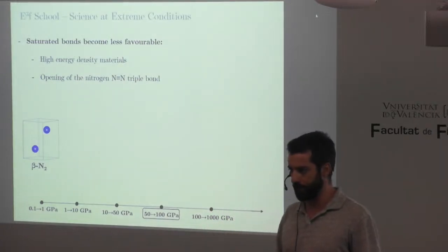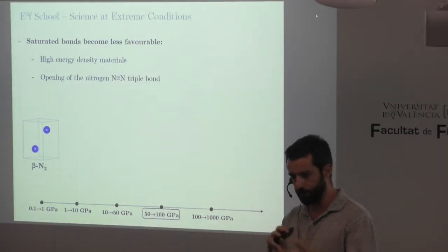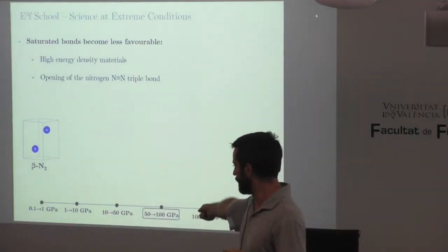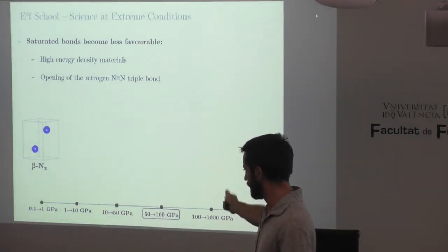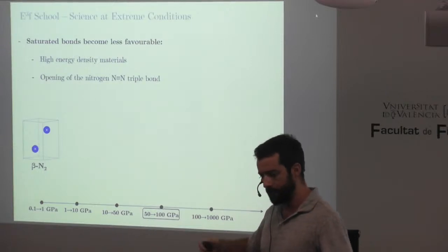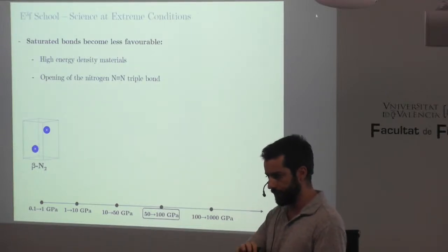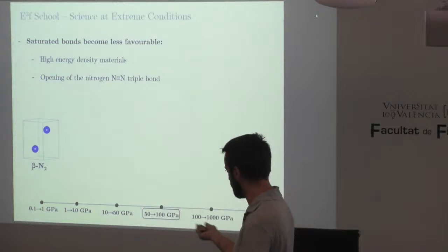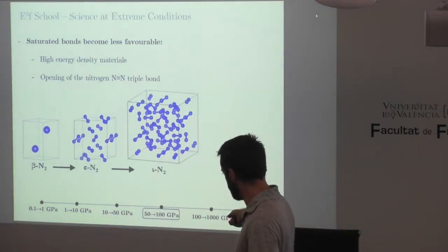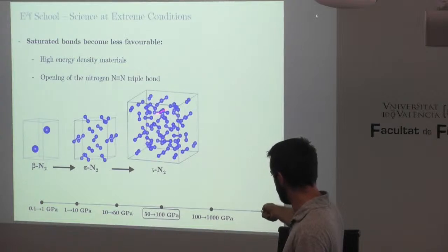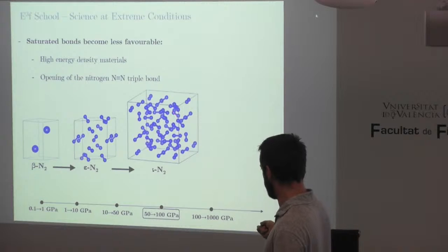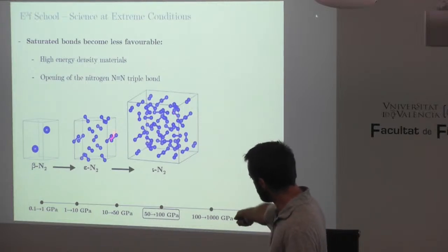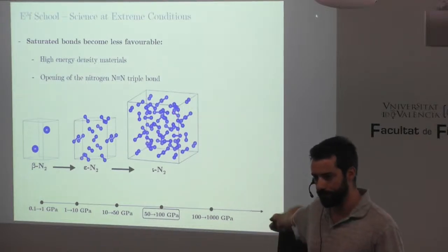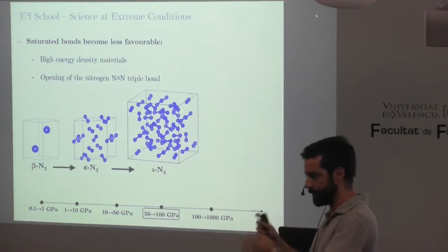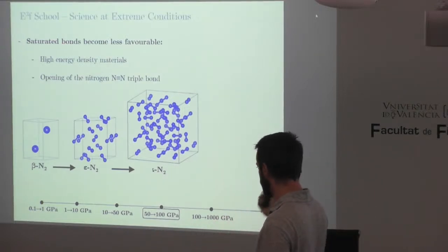Nitrogen exhibits approximately 15 different solid phases, different crystal structures. The first one you encounter when you increase pressure is the beta nitrogen phase. It's the most simple one. Then as you continue to increase pressure, the solid transforms into different crystal structures with increasing complexity. In fact, this monster here was the main result of my PhD thesis, which was published 4 years ago. But what these structures have in common is that they all consist of N2 molecules. There's no bonding between the nitrogen molecules.